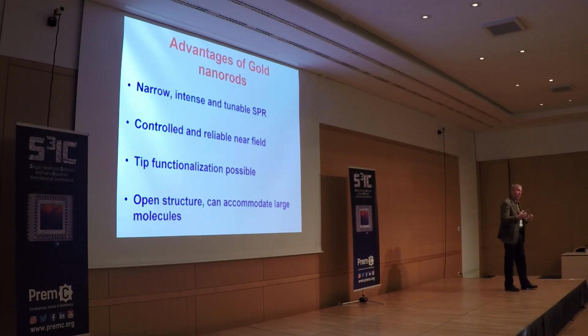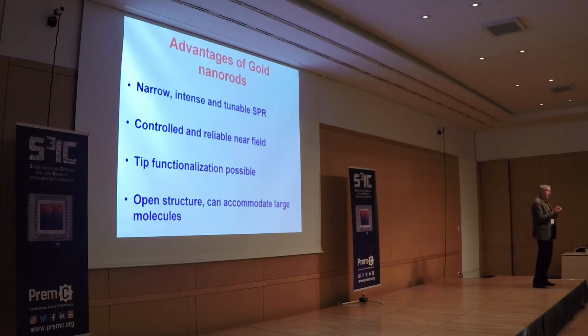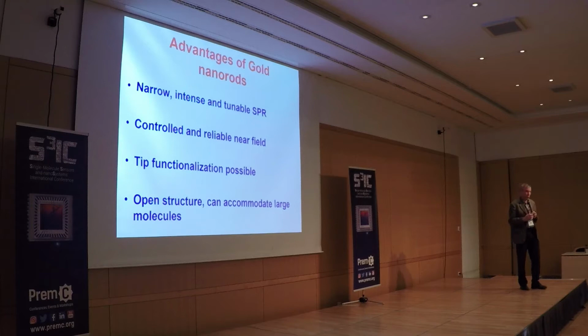And if you think of, for example, dipole antennas, which are formed of 2 particles, then you have a hard time fitting the molecule in a small gap. Right? It will be difficult to put a big molecule in a small gap without denaturating it or without damaging it. And this is something that you can bypass by using this very open structure of the rod. So those are maybe the most important properties that we like of these gold nanorods.